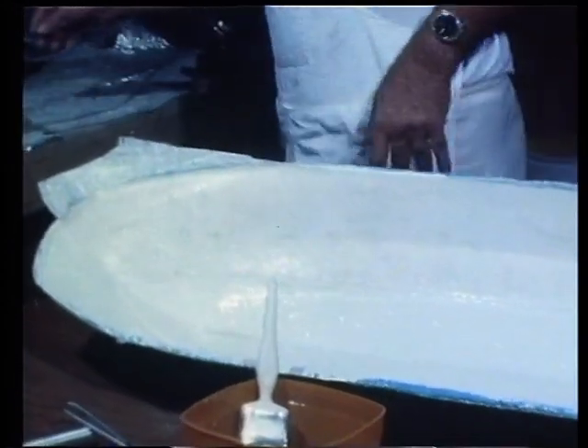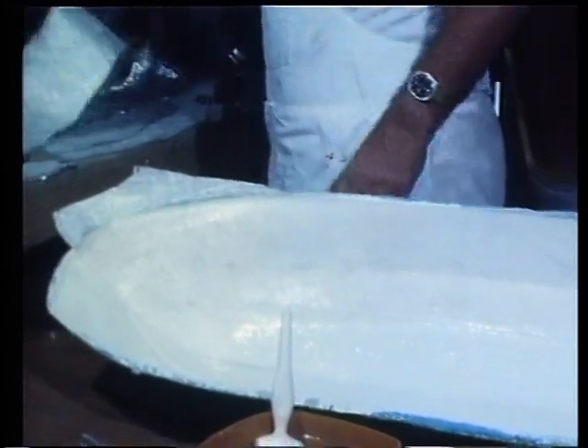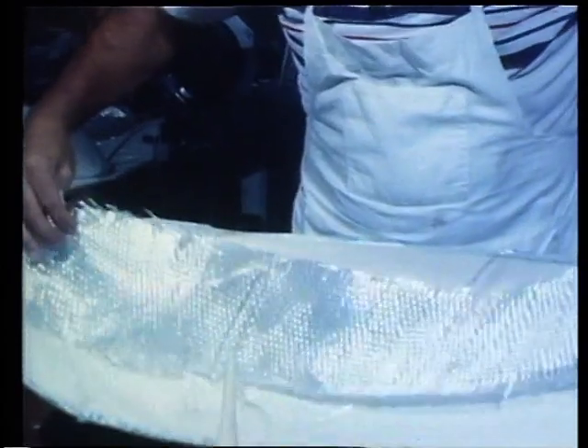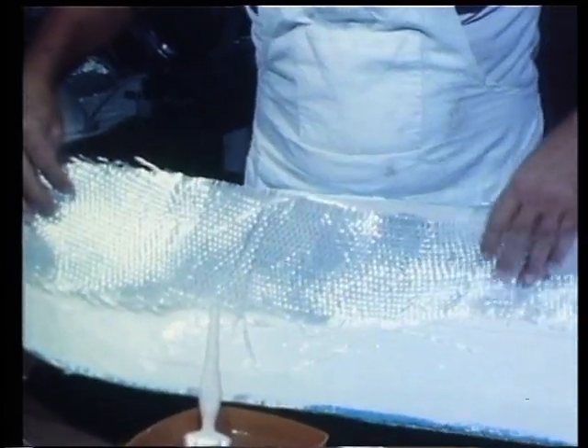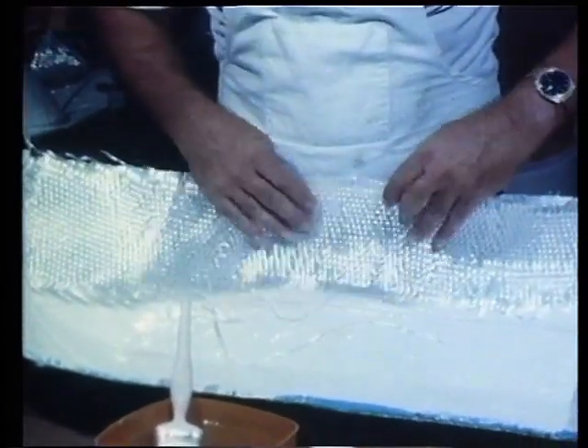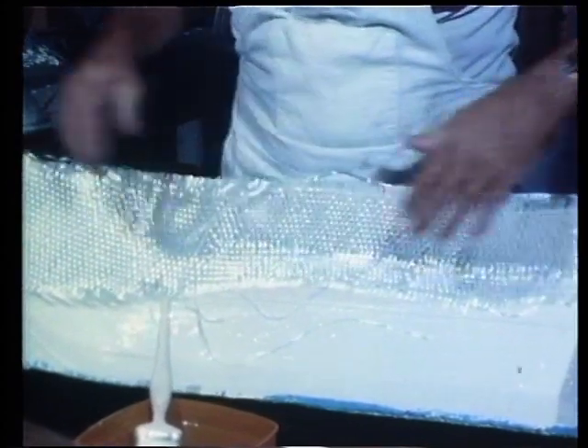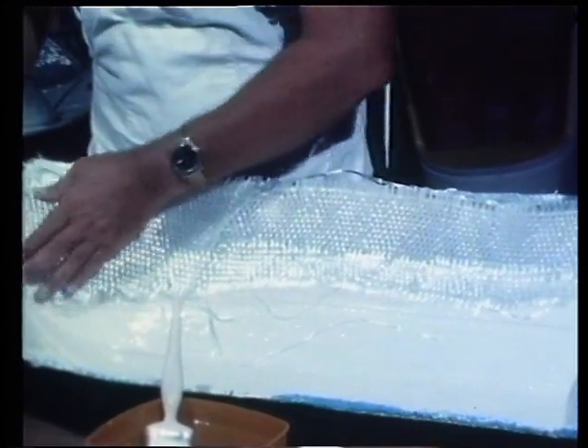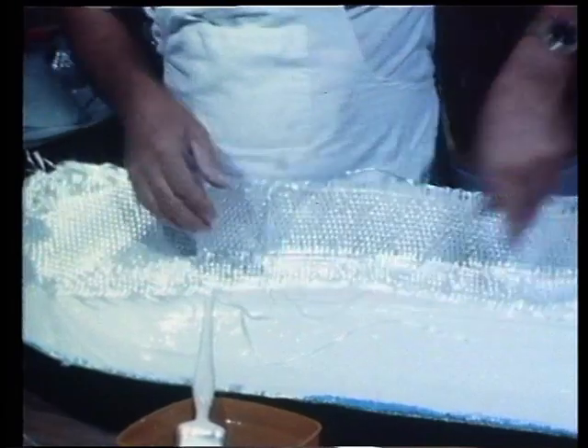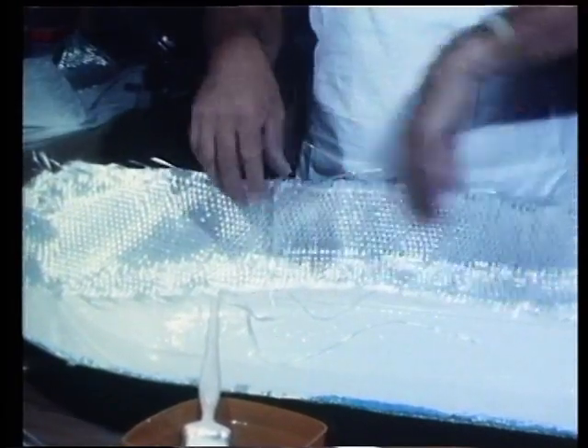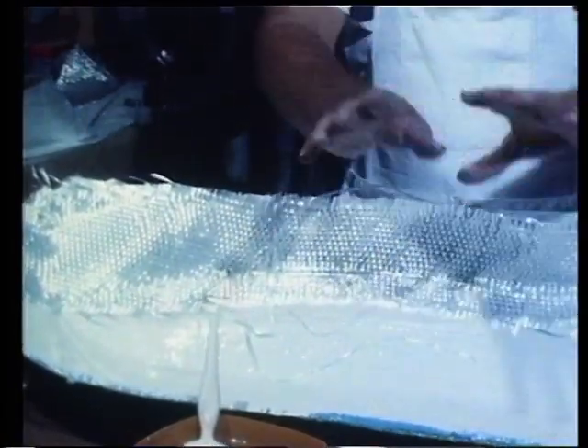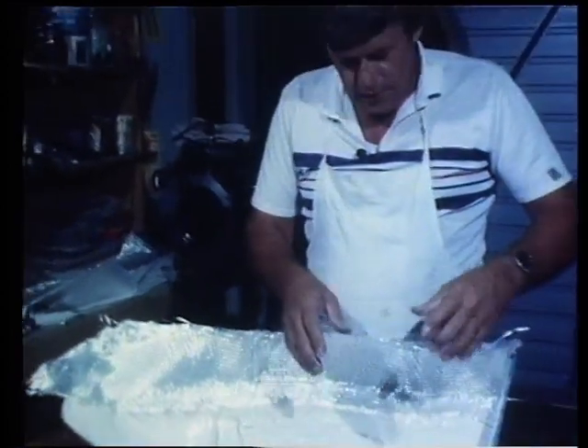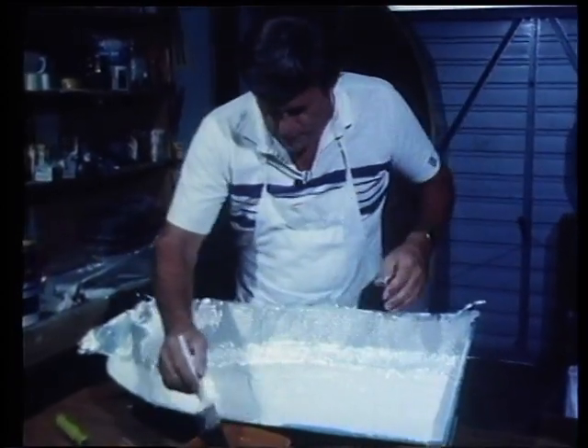The next step is to apply the woven roving. Now, this is not really necessary in a small boat of this size, but it's a material that's used universally in the production of fiberglass boats. So I'll put it in to show you just exactly how it's applied. Normally it would be rolled up in a large boat. It would be rolled up, put on the edge of the gunnel and just rolled down into the mould there so that it falls into position.